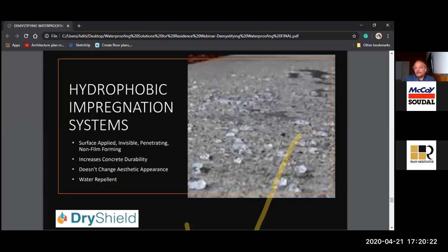Some of these products can penetrate up to 12.5 mm, 12 to 15 mm inside the surface, depending upon the porosity. Most of these being nanotechnology based products with nanoparticles, the particle size is very small. In some products, the particle size is smaller than the water particle size. So wherever water can reach in concrete, these products can reach almost, if not through and through, then almost 12 to 15 mm inside. And once they go there, they completely solidify in that area. As it's not on the surface, this is not a surface coating, so they don't form any kind of film on top, and they don't change any aesthetic appearance.